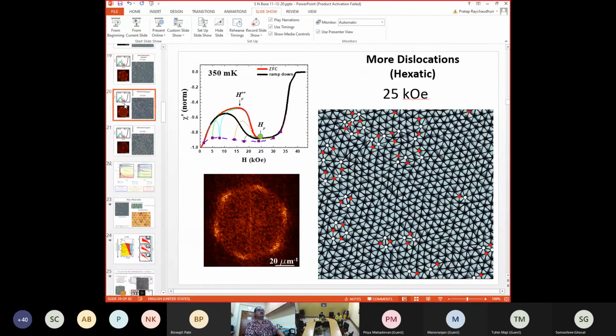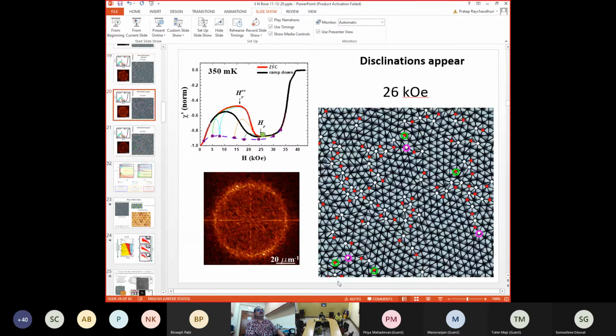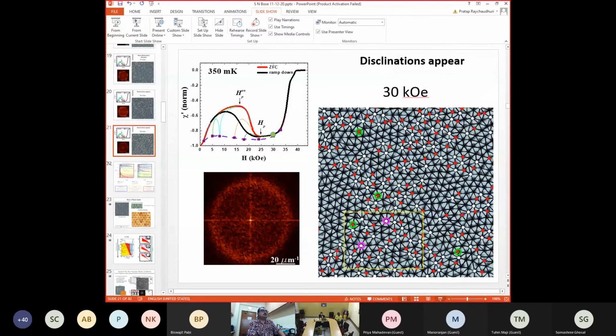and the moment you cross this HP, you see that now you have this disclination here. You have a disclination here, a disclination here, a disclination here. These are points that I have circled in green or purple for clarity. And now if you take a Fourier transform, you have a ring. Your orientational order is also destroyed. And then if you go further up, you have more of disclinations, and then eventually the vortices become so fast moving that your image becomes blurred and we cannot see anything.